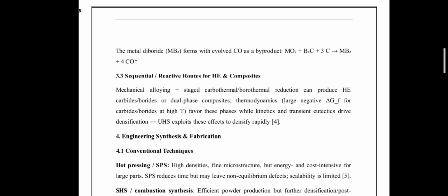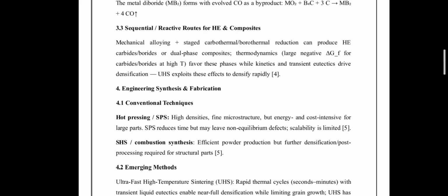However, densification is largely kinetically controlled. Transient or eutectic liquid phases accelerate diffusion and the reaction rate. Ultra-fast sintering techniques, such as ultra-high heating rates, exploit this kinetic effect to achieve near full density before excessive grain growth occurs. After studying the different types, now let's move toward the engineering synthesis and fabrication.